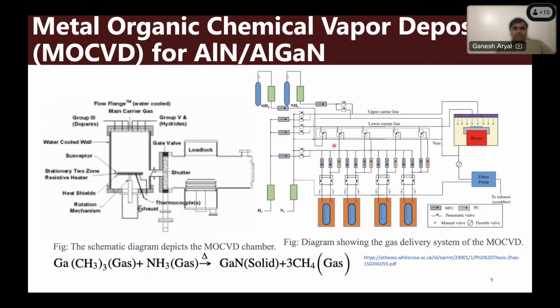So these schematic images show some parts of the MOCVD chamber. We usually grow our materials at around 1050 degrees Celsius, and there are a lot of parts in the MOCVD. We use hydrogen as a carrier gas, so the hydrogen carries the precursors of aluminum and other sources.